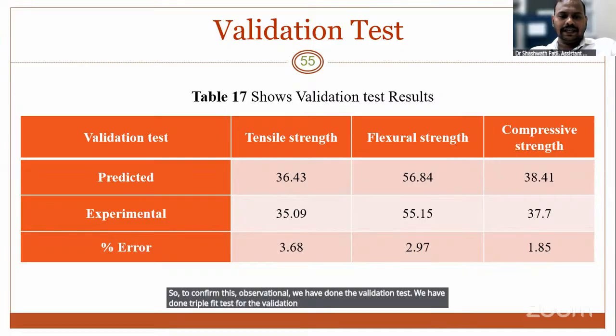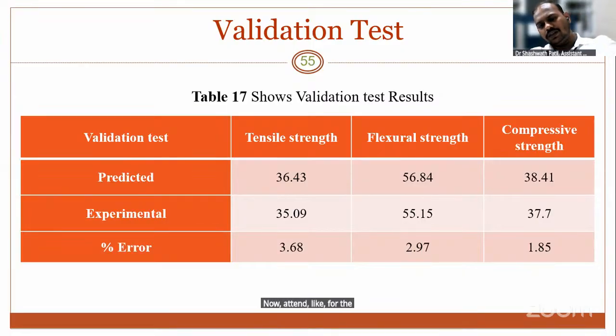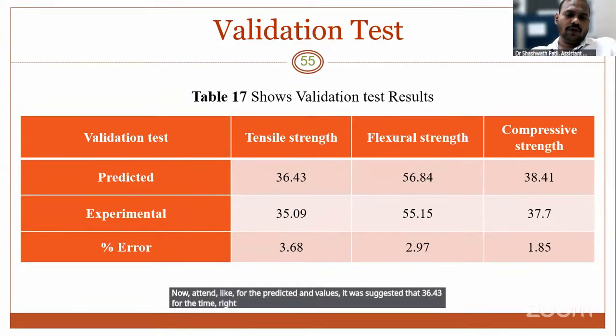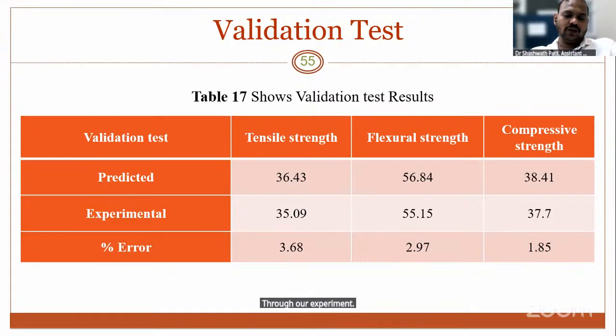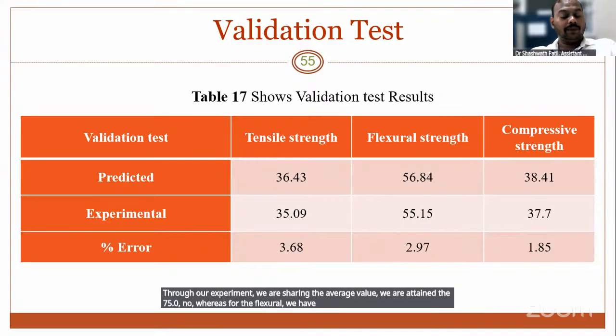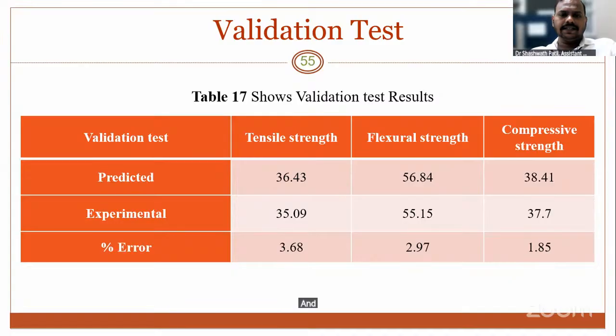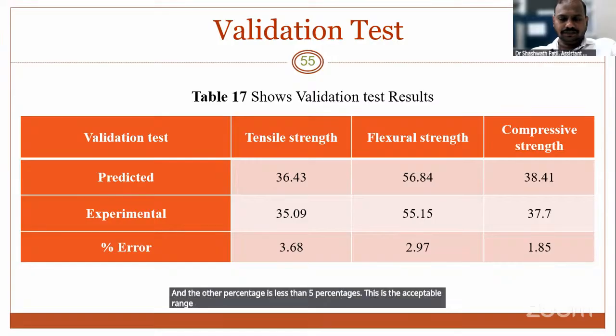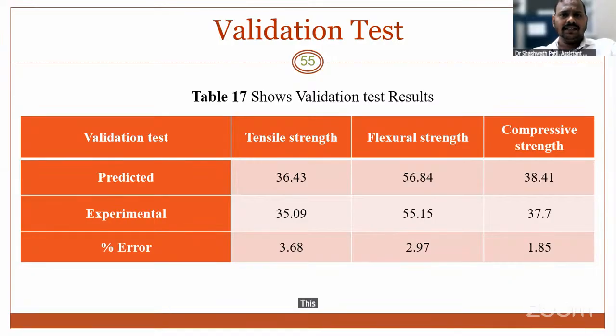For the predicted value, it was suggested that 36.43 for the sample. Through our experiment, we have attained an average value of 35.09, whereas for the flexural, we have attained 55.15, and for the compression, we have attained 37.7. In all three, we are near to the predicted value, and the error percentage is less than 5%. This is an acceptable range, and this shows that our model is significant.